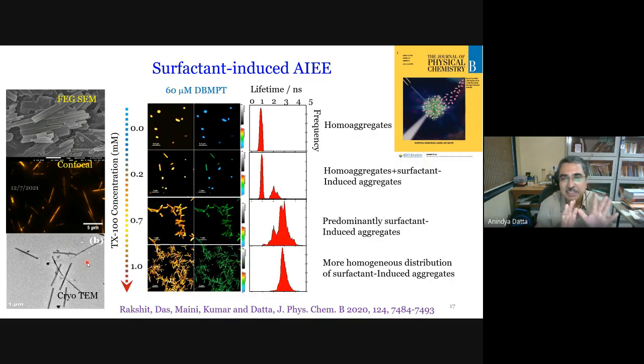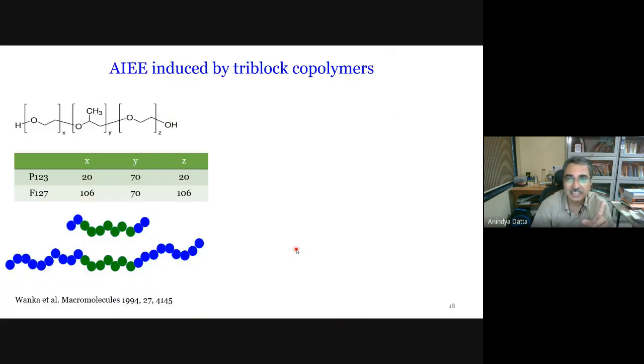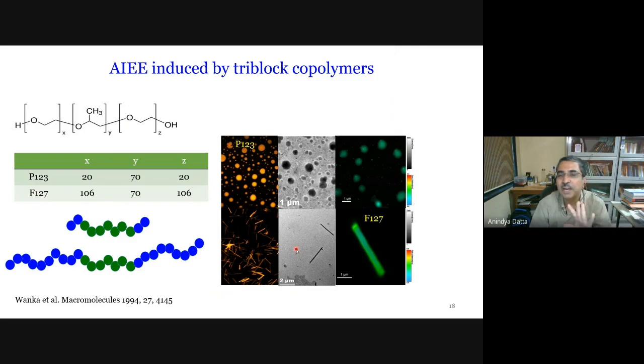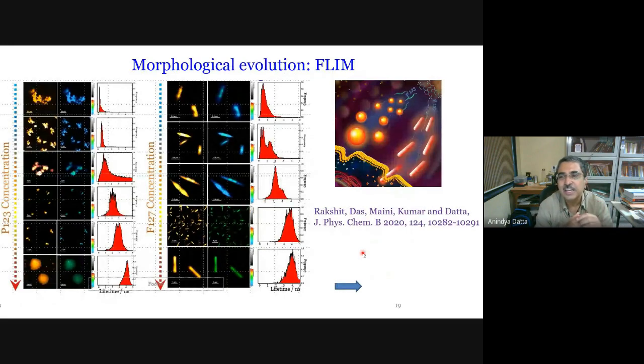Using fluorescence lifetime imaging microscopy, we could follow the morphological evolution of these nanorods, and we could see the modal lifetime going from something like 1 nanosecond to something like 3 nanoseconds. This is very preliminary data. We are trying to understand this in more detail, and some kind of simulation would be required to understand why we get nanorods, all the more so because of the results we got with triblock copolymers. We used two kinds of triblock copolymers, and we got two kinds of structures. With P123, which has a smaller hydrophilic chain length, we get microspheres, and with F127, which has longer hydrophilic chains, we get nanorods. Again, we followed the morphological evolution, and we found that the nanorods can penetrate the cell membrane while the microspheres cannot.